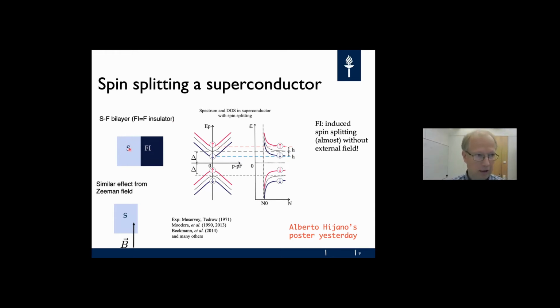Let's make a superconductor-ferromagnet bilayer, in particular with the superconductor and a ferromagnetic insulator, or you can also assume that a similar effect would be obtained by applying an in-plane magnetic field in the superconductor. And if the superconductor is a thin film, the orbital effect does not play a big role.